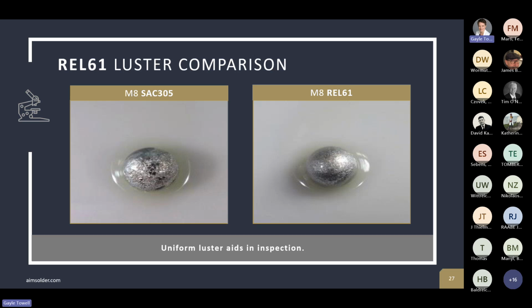And this matters because if you run your boards through AOI inspection, AOI inspection works by shining light on the solder joints, and that light reflects off, and the computer interprets what it sees to try to determine if the joints are good or not. And if you have a non-uniform surface that you're shining off of that has some smoother spots, some shinier spots, you can end up with interference in the data. You can end up with false calls on your AOI equipment.